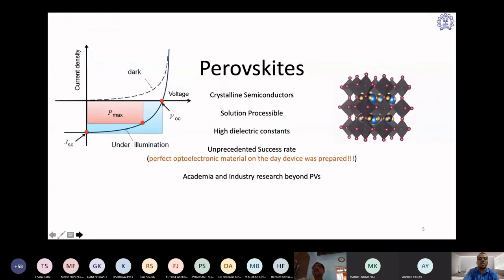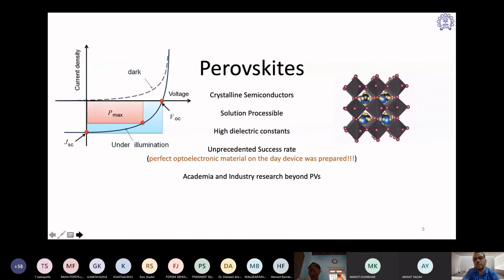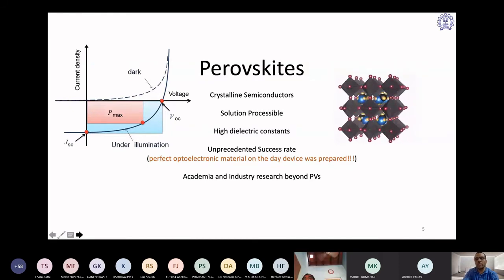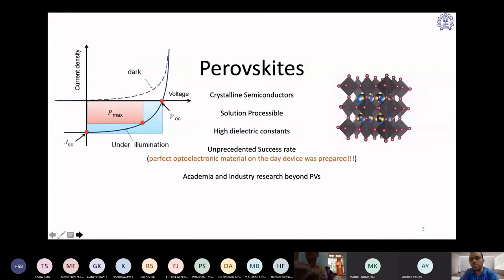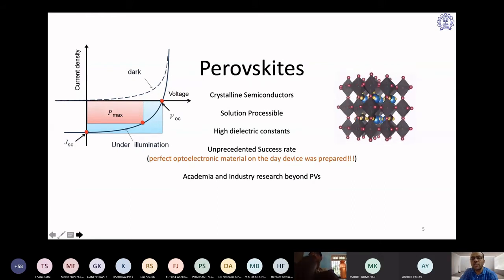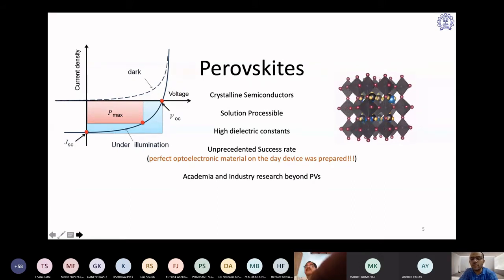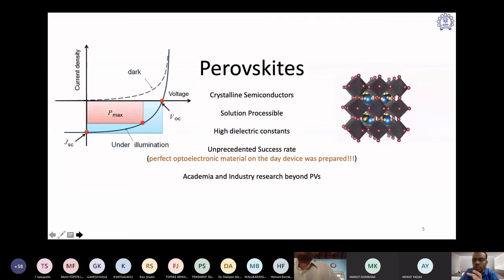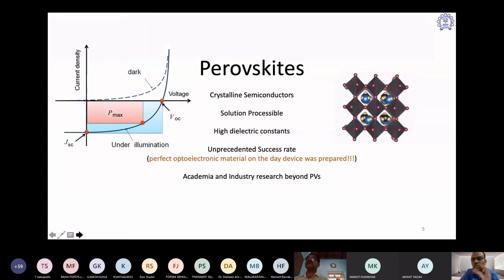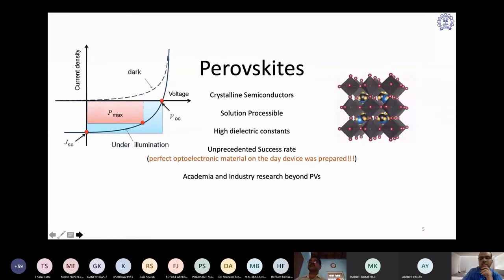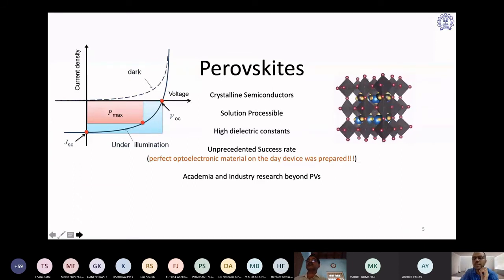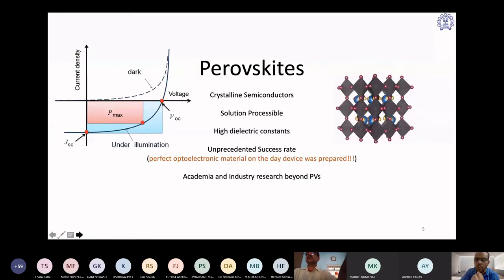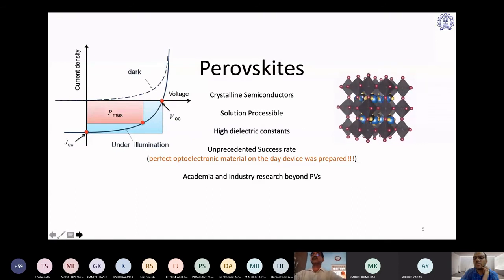So the beauty about this perovskite is, here I'm showing a GIF image of the perovskite. You see nice corner-sharing octahedra of PbX6, and in between those voids, the methylammonium ion is sitting, and this methylammonium ion has got lots of extra room to wiggle around, to move around, and that basically makes it electronically active. Once you shine the light, which is always what?